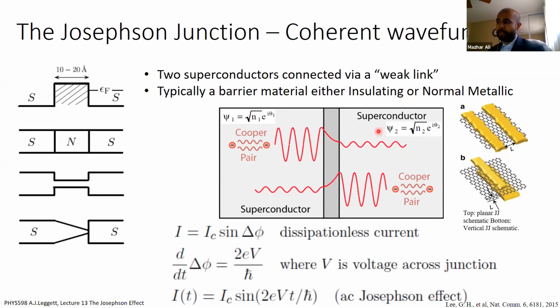But the takeaways, of course, were the main Josephson relations, where one, you have a sinusoidal dependence of the current on the phase difference between the two superconductors, and that at a constant voltage, you'll actually have the current ringing. That would be the AC Josephson effect. And you can make these in either planar or vertical junctions, so across a barrier material literally above and below, or in a plane. In a plane, typically these lengths are much longer. You're limited by, for example, e-beam lithography resolution, so at the minimum this is typically maybe 50 to 80 nanometers long.